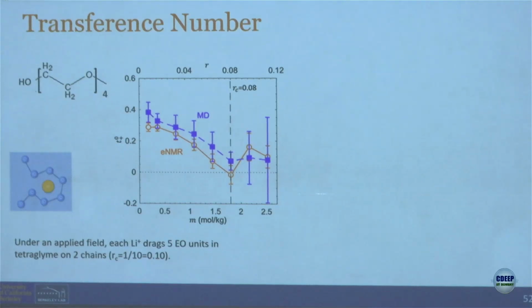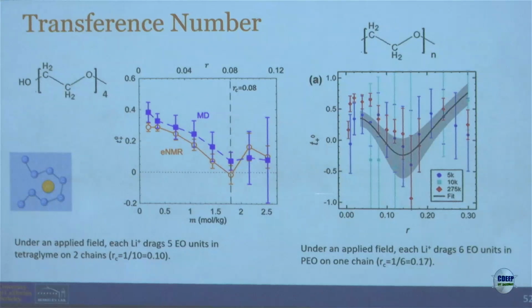The orange symbols are the NMR measurements. I'm not belaboring the molecular dynamics simulations, but it's pretty nice agreement. And you can see that it has an odd shape. It sort of starts out at 0.4. It goes down to something like 0 and then comes up. Not very different from that PEO horrible thing that we had published based on the standard way of looking at things. And because this has 4 oxygens and you need 6 oxygens to have a solvation shell, you drag 2 of these chains along with us.